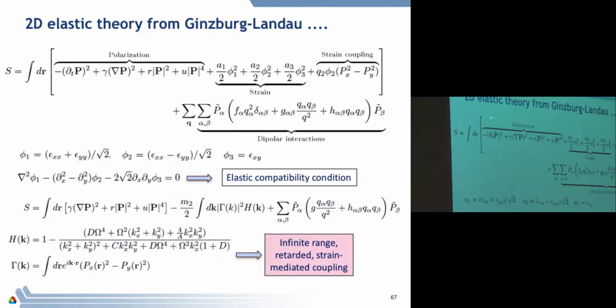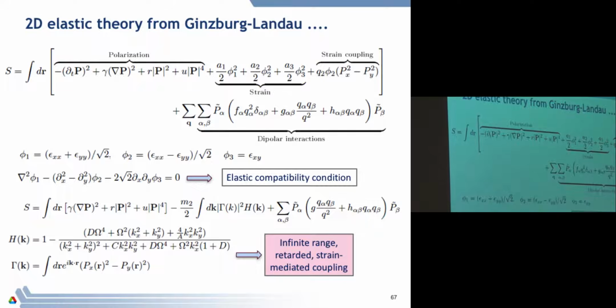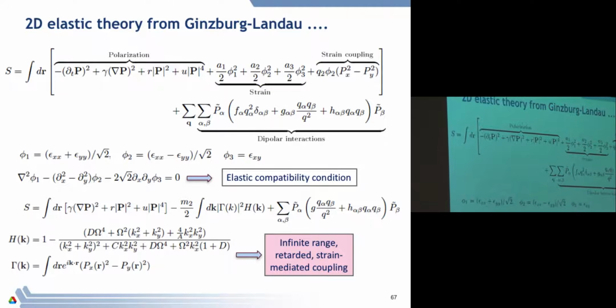There's a kinetic term, and then of course there's a so-called gradient term. That's how costly fluctuations in the polarization would be. If I want to make the polarization inhomogeneous, if gamma is large, it penalizes fluctuations from place to place in the polarization, and if gamma is small, they're easy to have.